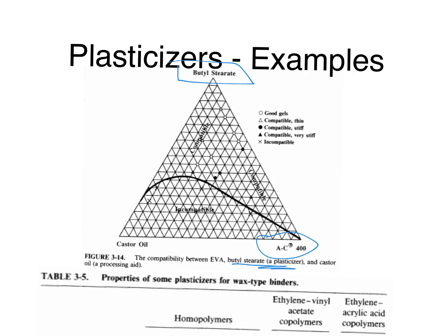Butyl stearate is a plasticizer, what we just mentioned. And then there's also, interestingly in this one, castor oil, which is acting as a processing aid. This is a low molecular weight oil, but it has functional groups that will attach it to the aluminum oxide, if that's your processing, and then have a polymer chain that comes off the surface. And then we have the plasticizer, the butyl stearate, which makes everything softer, and then this ethylene vinyl acetate, which is the AC400, and that's the workhorse polymer, the high molecular weight polymer.